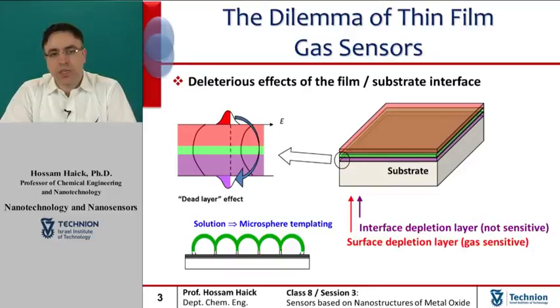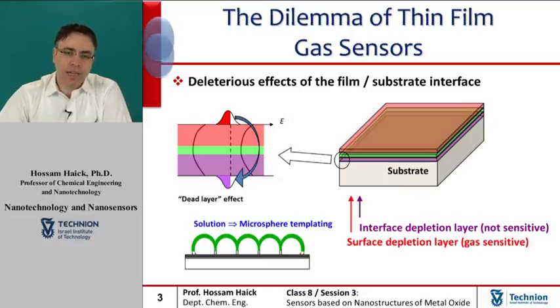One option is reducing the film thickness to dimensions comparable to the depletion length, namely 10 or 20 nanometers. But in this case, stability problems due to film-substrate interactions and other adverse effects connected with the film-substrate interface become so critical that improvements in the performance are not achieved. In order to get around these disadvantages, a simple yet effective solution was developed.